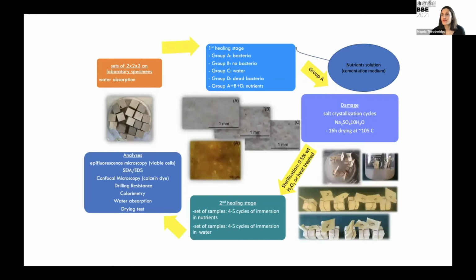So following the first round of experiments, the second healing stage aimed at investigating the possibility of having bacteria spores which would survive harsh conditions and contribute to further mineral formation. So we took specimens from Group A that were treated with bacterial nutrients during the first healing stage, and we subjected those specimens to salt crystallization damage and sterilization. The specimens were then divided in 2 sets. One set was further supplied with nutrients after damage, while the second set was only supplied with water for comparison.